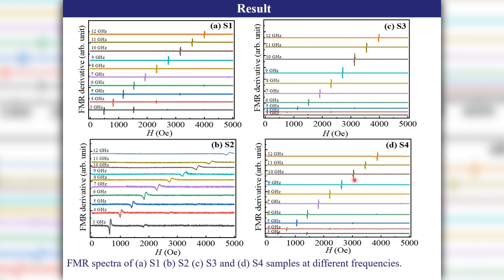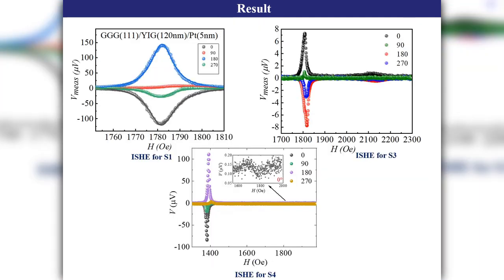And the same for the other bilayer, we use these FMR data to find out the H resonance and delta H, and then further find out the damping values, and finally we are measuring the spin pumping voltage also across them. And now this is just a preliminary graph of the spin pumping voltage that we determined for the YIG platinum, and this one is for TMIG YIG. As you can see for the S3 sample, this is the absolutely TMIG spin pumping value, and this is obviously the YIG which has a higher value.